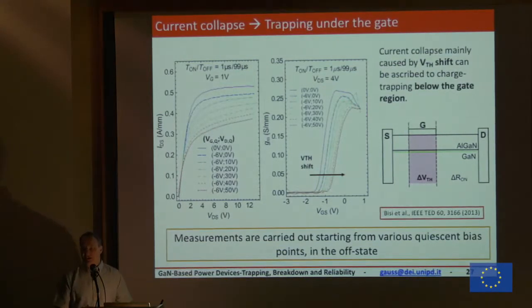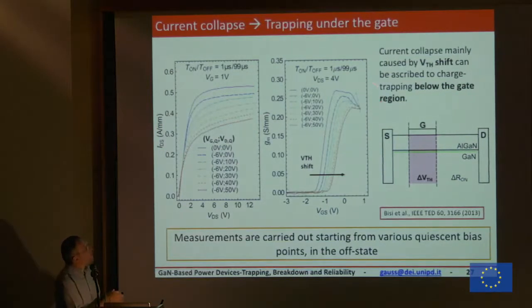Here, the basic electronics tell me that this problem is related to something happening under the gate. So electrons are trapped under the gate because I don't see a huge drop in the transconductance, just a threshold voltage shift. So I am changing the potential under the gate. So this, let's say, helped me to localize the traps. In this device I can tell you what was happening. It was just a lot of trapping at the interface between the gate and the AlGaN layer. Okay.